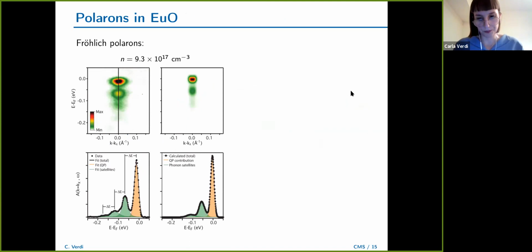Since they knew that we did this sort of calculations for TiO2, they asked us to do the same for europium oxide. And indeed, we observed this satellite replica when we calculated the spectral functions, including a self-energy that had the interaction with longitudinal optical phonon. By the way, I probably never used the name Fröhlich before, but this sort of interaction with longitudinal optical phonons, which is a long-range interaction, is often named the Fröhlich interaction, since Fröhlich is the one who first wrote the Hamiltonian for that. So this is quite satisfactory.